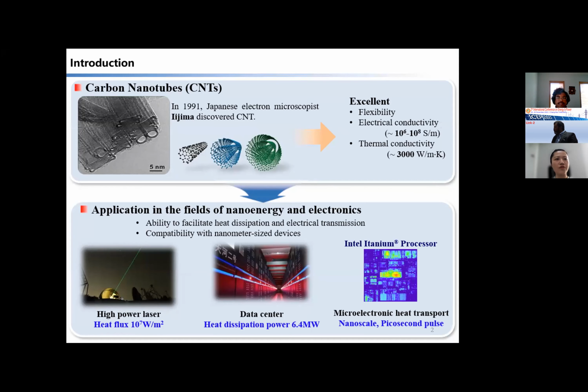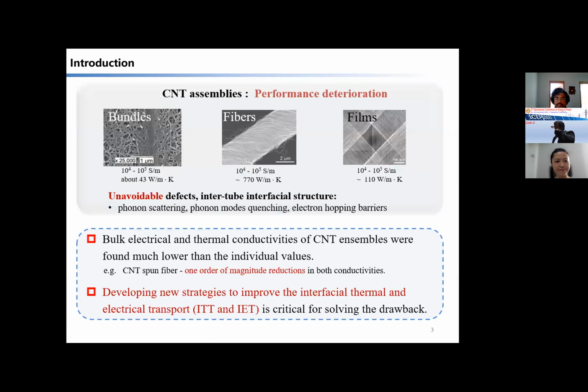Electron and phonon transport of carbon nanotubes has attracted much attention in the field of nanoenergy and nanoelectronics due to its ability to facilitate heat dissipation and electrical transmission and compatibility with various nanometer size devices. However, once assembled, such as into bundles, fibers, and films for practical application, CNT tubes exhibit considerable performance deterioration due to phonon scattering, phonon mode quenching, electron hopping barriers, and the numerous intertube interfacial structures acting as energy transport barriers.